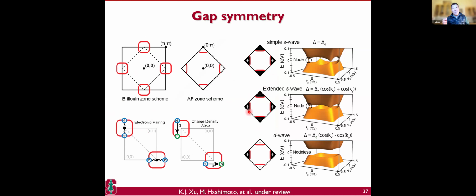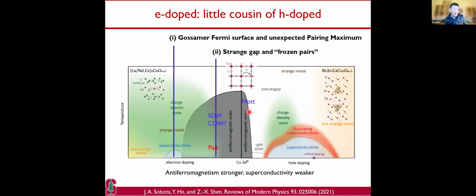I should also point out, in this case, the s-wave should have a node, and the d-wave should not have a node, okay? Because the Fermi surface has already been reconstructed by the antiferromagnetism, so you have a sign change once. Therefore, for the d-wave, if you sign change another time, you won't have a node. I won't go into the detail, but this is where we are now. I hope to give you a sense of these two pieces of recent work. One is the Gossamer Fermi surface, and that tells you something about the nature of the pseudogap. Certainly in this case, antiferromagnetism plays a very important role, but it also shows how clever the electrons are. They're able to use their two degrees of freedom to do these two interesting things.